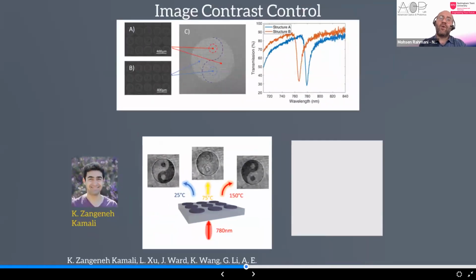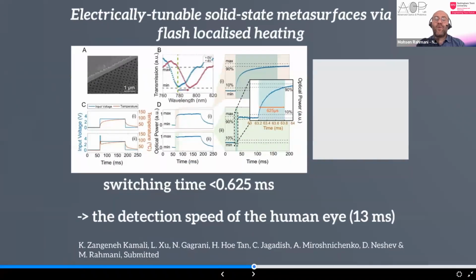So the issue here we had was the time of heating, and the question all the time we received was how long it would take. Because we were using actual heaters, it would take maybe around 10 minutes to heat it up and then cool it down to come back to the first phase. But all the time we were receiving the comment that the time is not good enough for real application. That's why Khosrow put a lot of effort and time to come up with a nice way to use the same phenomena electrically.